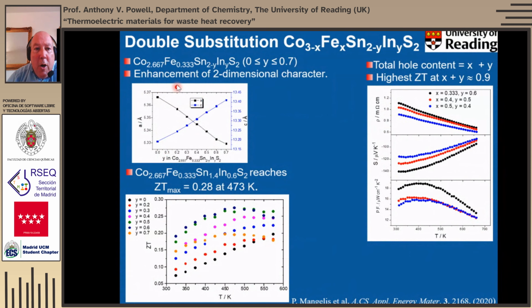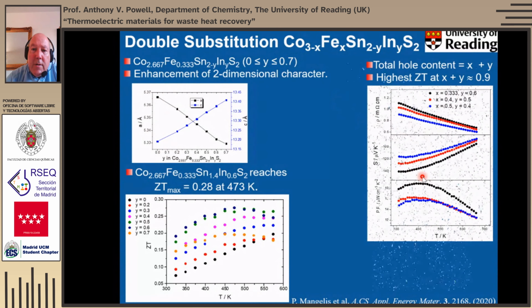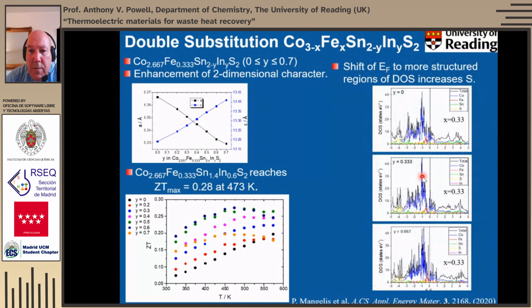Now, we've done quite a lot of combinations of cobalt, iron, tin, indium, but what we find is that the highest ZTs are always at a similar total hole content. So that is when the iron content, which is given by X, and the indium content given by Y add up to 0.9 or thereabouts. So here are 3 different compositions with 3 different values of the iron content and the indium content, and you can see the properties are all quite similar. So there's something about that 0.9 hole content that is important. And from our band structure calculations, we find that what we're doing really when we go towards 0.9 is we're moving that Fermi level more and more into a highly structured density of states.